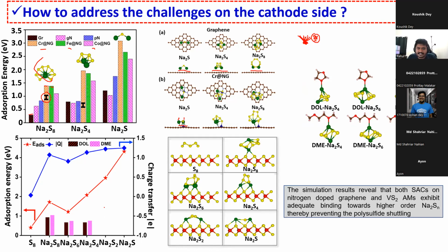Now we also use a VS2 based material. VS2, as I told previously, is conductive in nature. This is the interaction energy between the electrolyte and the polysulfide. You can see clearly that compared with the electrolyte's interaction energy with the polysulfide, the interaction energy between the VS2 and the polysulfide is very high. That means the VS2 material can also trap the polysulfide rather than sending it to the electrolyte. This is the binding configuration: Na2S to VS2, Na2S to VS2. We converted the structure and later calculated the adsorption energies.